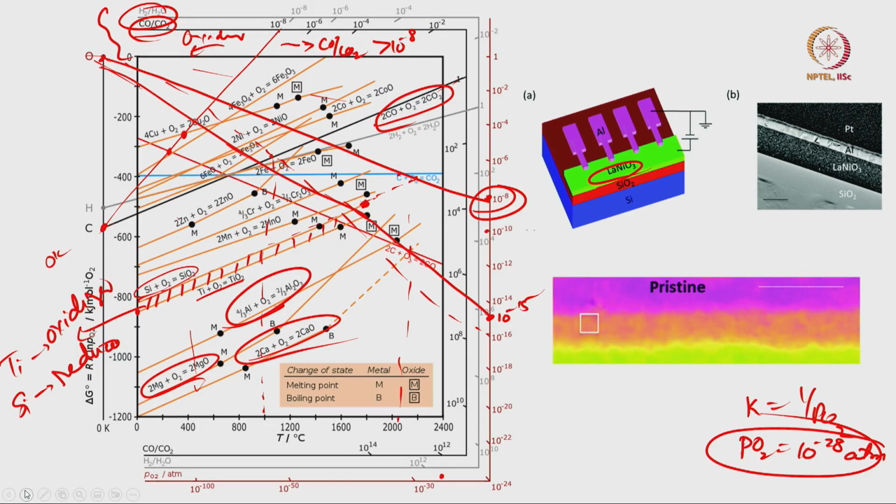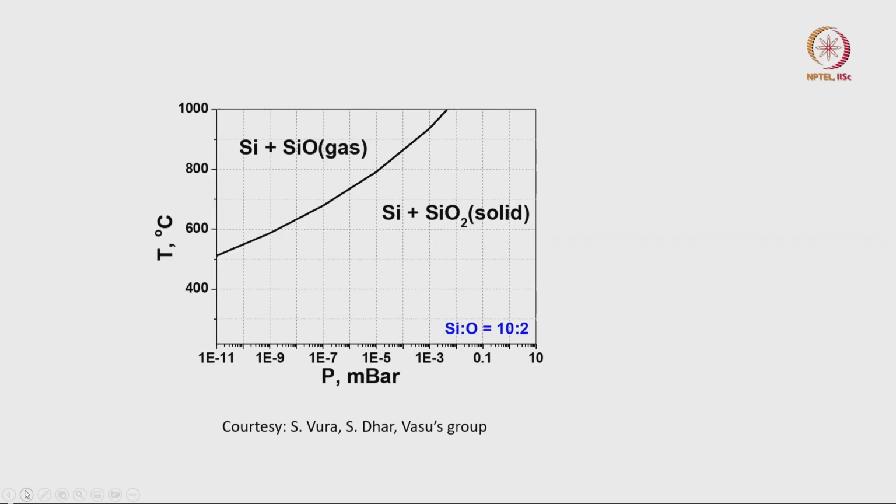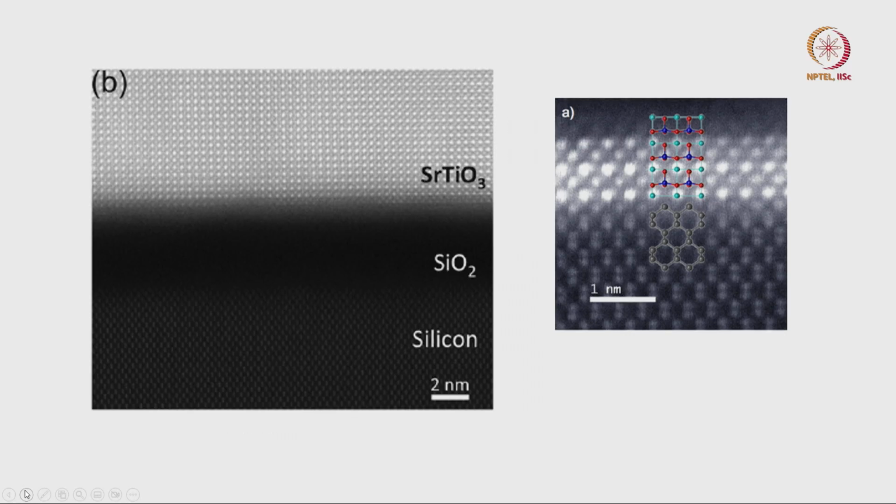Okay. So, same thing, right. If I just point out other examples. Yeah, same thing. Here people have grown strontium titanate on silicon. Again you see this SiO2 layer, this is a reformed SiO2 layer, but the titanium is reactive enough that initially it starts forming seeds, and on the seed you start growing the strontium titanate, and then later the silicon oxide again reforms, right, and so on.